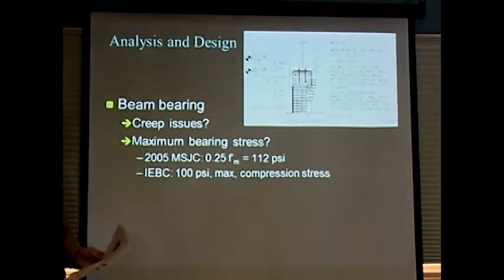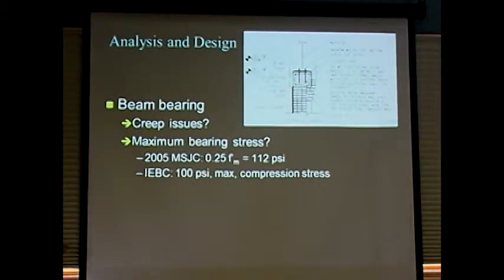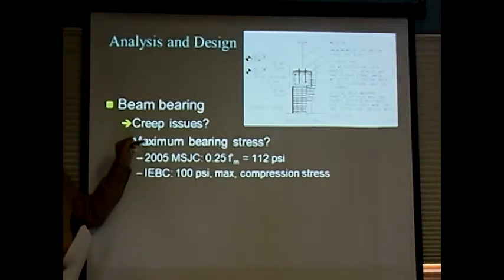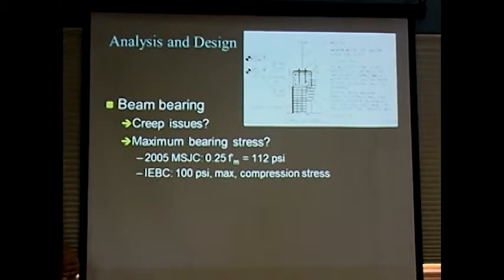And that's pretty interesting. So the first step really was designing a reinforced concrete bearing pad, if you want to call it that, underneath the beam bearing points. And originally, these walls were designed by the engineer to be under about 200 psi stress. Sounds pretty low, but remember I told you, what was the compressive strength? Somewhere between 400 and 500 psi. 200 psi is way too high.